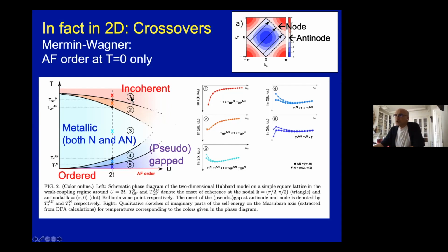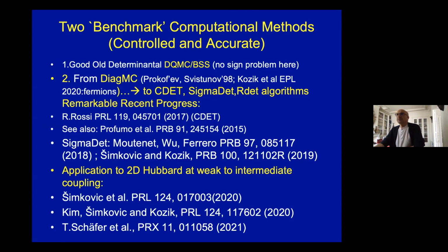In the incoherent soup here, you have something that diverges at low frequency, and then it becomes coherent in the metallic regime 3. And then at very low T, the formation of the insulating pseudogap is again characterized by some sort of singularity at 0 frequency in that quantity. So looking at this quantity, one can actually diagnose these different regimes.